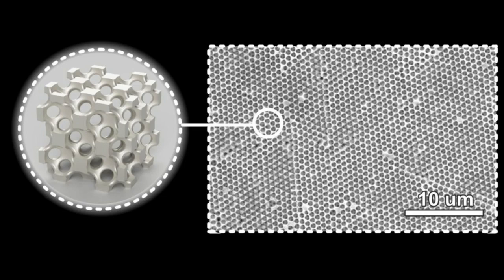These inverted cracks stem from the way that metallic wood is made. It starts as a template of nanoscale spheres stacked on top of one another. When nickel is deposited through the template, it forms metallic wood's lattice structure around the spheres, which can then be dissolved away to leave its signature pores.